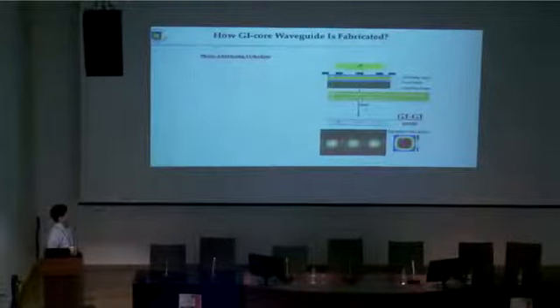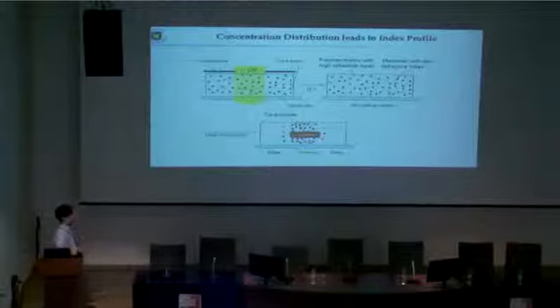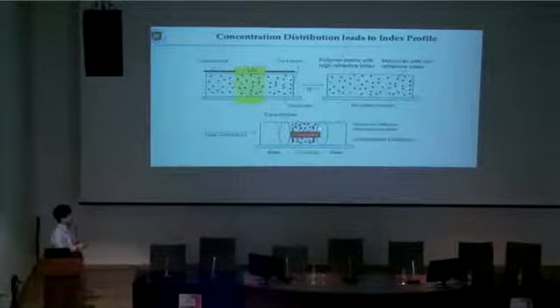That is the mechanism to form the graded index structure in this square core. And this is a very high secret, so I do not know how to adjust this condition. But not only in the horizontal direction, but also in the vertical direction, they could reach the concentration distribution to obtain a completely graded index structure. So we name this structure GI profile, while this one we call SI-GI. Okay, so here is the mechanism. After UV curing, in the illuminated area the cross-linked structure is formed and the volume contraction is observed. Then some monomers diffuse into this illuminated area. Then the concentration of this monomer is higher, which increases the refractive index in this area. And then the graded index structure is formed.